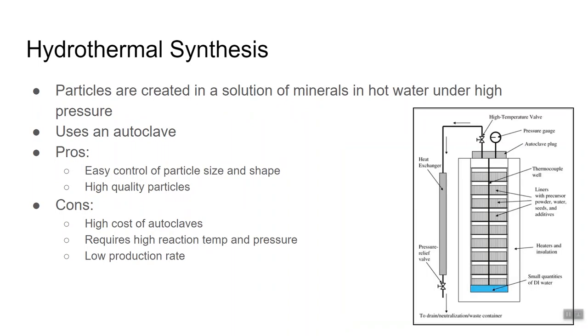Next is hydrothermal synthesis. This process is about creating small crystals of the target material in a solution of minerals in hot water under high pressure, and this is typically done in an autoclave. The process requires you to heat a solution at a specific temperature and pressure for a set period amount of time, followed by drying processes.